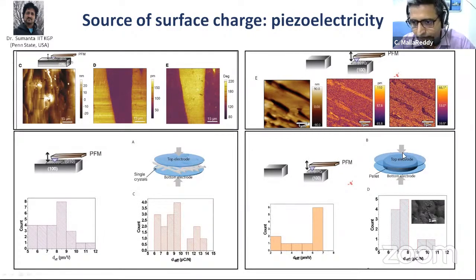So even in the pellets, we saw that there is a slight drop in the piezoelectric response, and this is not surprising. This is true for most piezoelectric materials. When you deform them, when you have a lot of defects, the piezoelectric response is expected to be slightly lower.